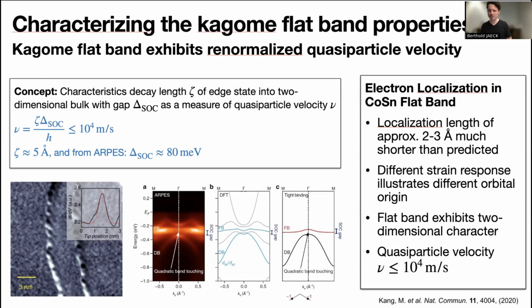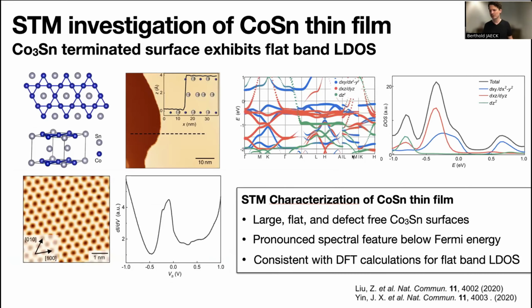So what most people have done to calculate these band structures, ourselves included, is simply to switch off the magnetic interaction in DFT. So this band structure, which we now take at face value, is not accurate quantitatively. And we also believe there are interaction effects in these d-orbitally derived bands that should be stronger than what DFT can capture within these limitations. All right, thanks. I think Jose was first.